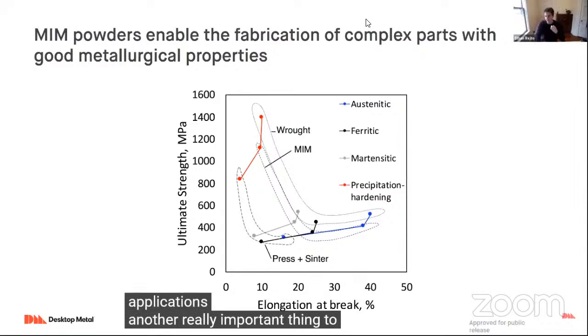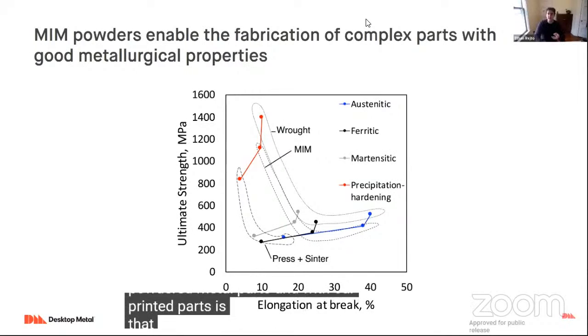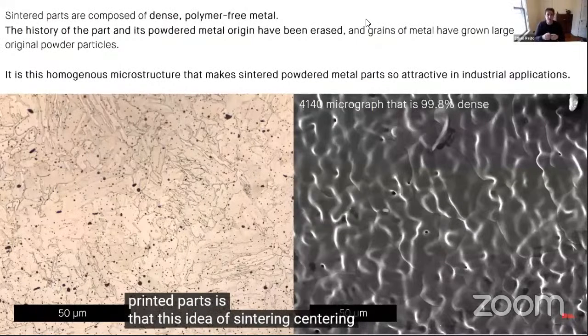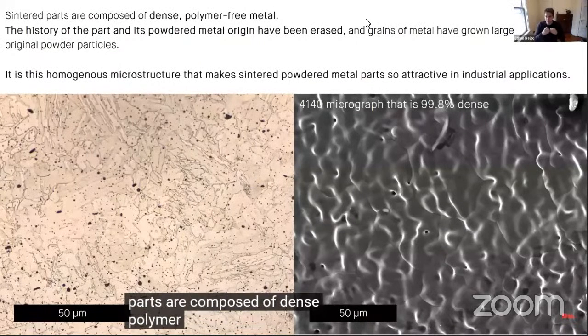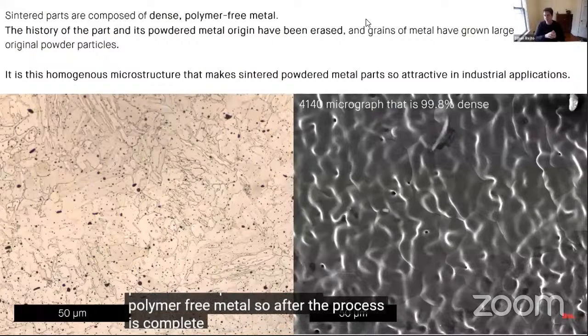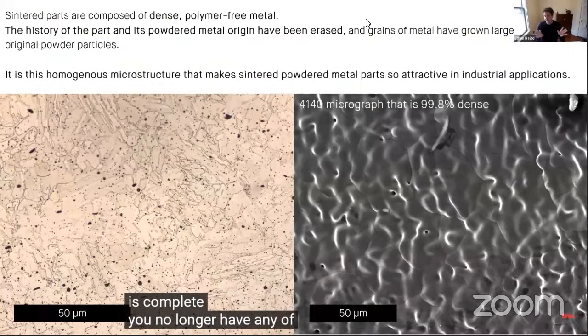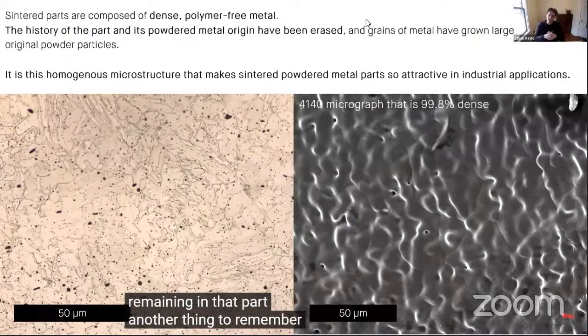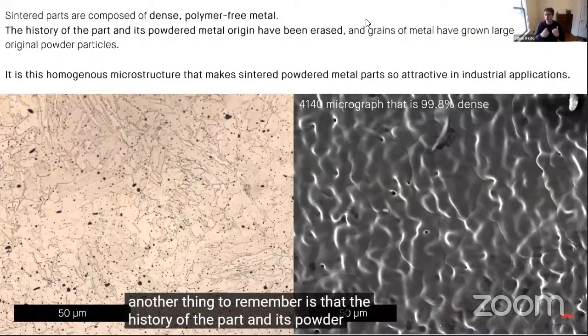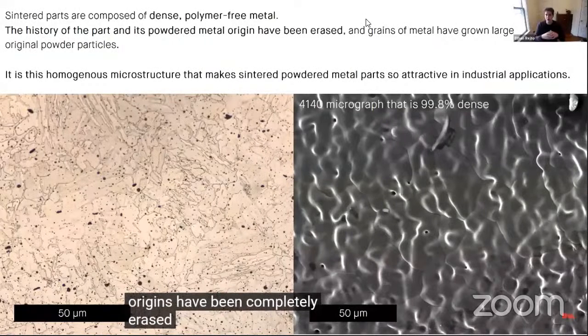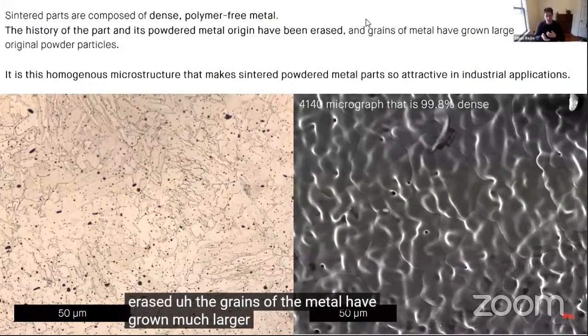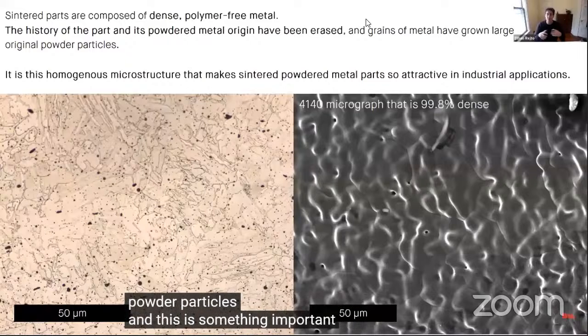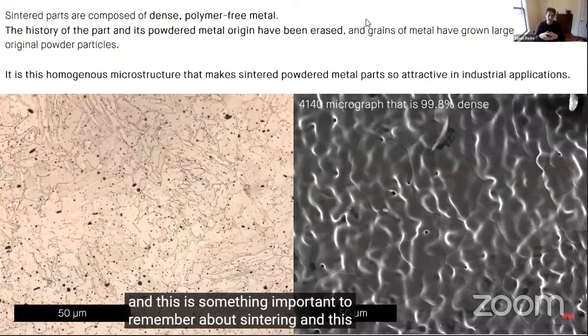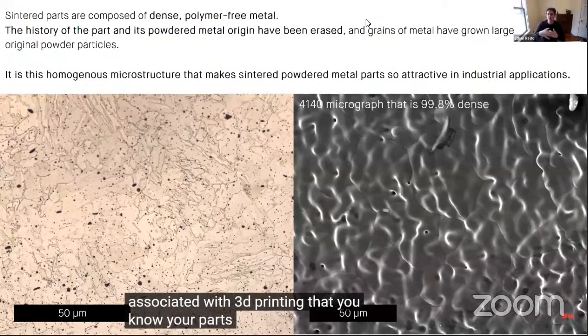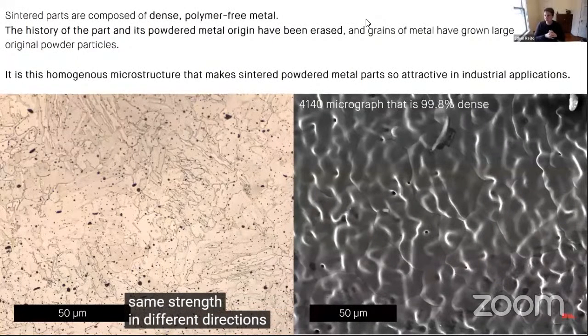Another really important thing to remember about powdered metal parts and our printed parts is this idea of sintering. Sintered parts are composed of dense, polymer-free metal. After the process is complete, you no longer have any of that binder remaining in that part. Another thing to remember is that the history of the part and its powdered metal origins have been completely erased. The grains of the metal have grown much larger than the original powder particles. This has long been associated with 3D printing, that your parts are not going to be the same strength in different directions because of the layers.